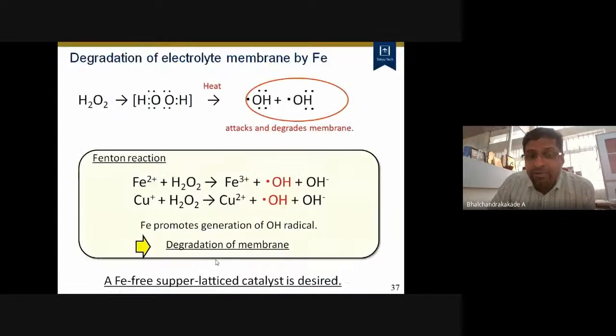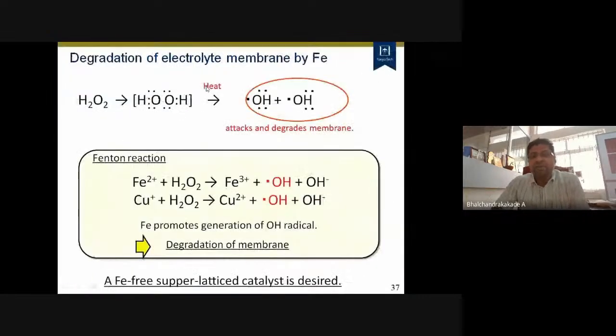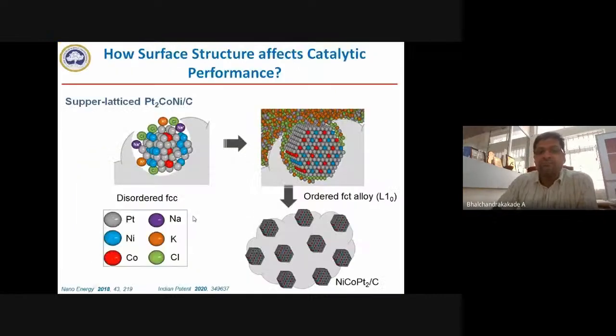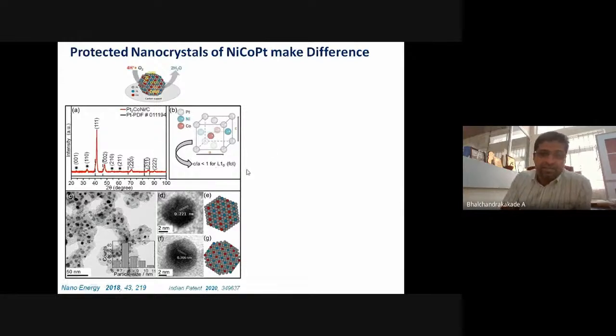That was our idea. But when we looked at iron-containing catalysts, we saw the very famous Fenton's reaction. The Fenton reaction is promoted by iron and copper when peroxide is formed. Whenever peroxide forms in the presence of iron and copper, OH radicals form, and these OH radicals become very, very challenging and problematic for electrolyte stability. So we started avoiding iron. Then we developed Pt2CoNi structures, which give us a very interesting surface, called the face-centered cubic structure of Pt2CoNi, where we have 2 Pt, 1 nickel and 1 cobalt.